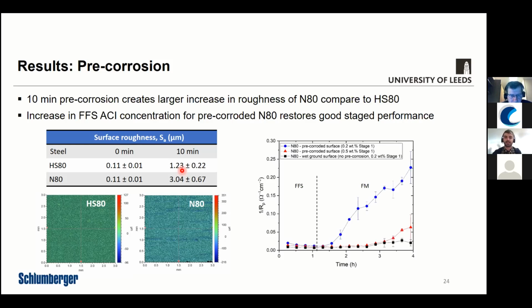So what we did as a solution, and this is one of the convenient things of this test methodology and the staged approach, is that by varying the film form stage concentration, we could increase the concentration during this stage so that we could protect the steel more effectively. So what we did was increase the film forming stage, stage 1, concentration to 0.5 weight%. So this is the red line here. While still maintaining a 0.01% stage 2. And what we saw again was much more acceptable corrosion rates. We didn't see as significant an increase at the end.